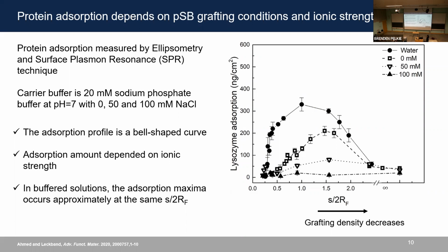However, as more and more salt ions are present, as we increase the ionic strength of the solution, there is now competition for the ions with the polar or the charged sides of the side chain of the polymer. And we see very low adsorption when the density of the brush is very high, which represents the scenario of the ultra-low fouling properties of polysulfobetaines that has been reported in many previous literature. So with that,